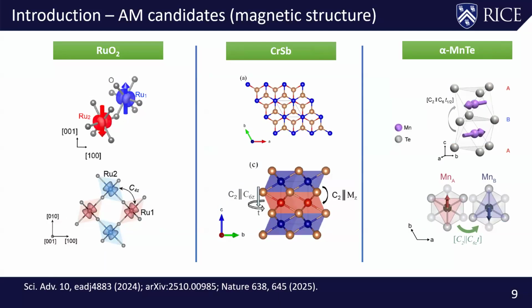The first prototypical example of an altermagnet is the famous ruthenium dioxide. This material, at least in thin film form, was found to exhibit some anomalous Hall effect, and people thought this may be the first example of an altermagnet. But subsequent measurements have shown conclusively that, at least in bulk, this material has basically no magnetism.